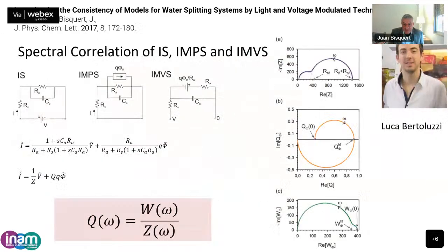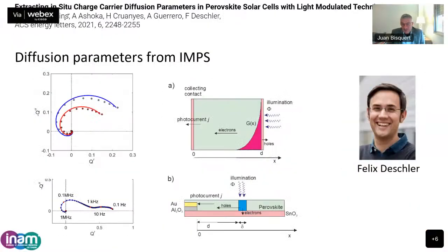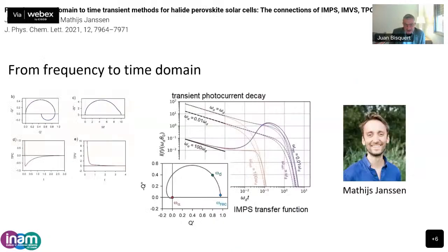And the reason is that the measurement is not really the same, because, as I said, you can observe this negative part when you make a very short distribution of electrons by strong absorption, and then you make them cross the sample, and this doesn't happen in impedance spectroscopy because it's just an electrical characteristic.